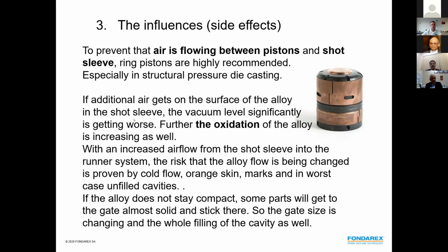Then another big point is always the plunger and the shot sleeve. Shot sleeve, even without vacuum, the better the shot sleeve and the better the piston, the better the castings in general. In vacuum die casting, even more important. So for standard die casting parts, maybe even with the help of vacuum, we are able to make good castings also with standard pistons. The problem is we probably have to exchange them every 3,000-4,000 shots. If we have a ring piston, if it works well with the application, with the shot sleeve, the ring piston works up to 10,000 shots before changing a ring. So therefore, for a longer time, we are having a tight system for using the vacuum.